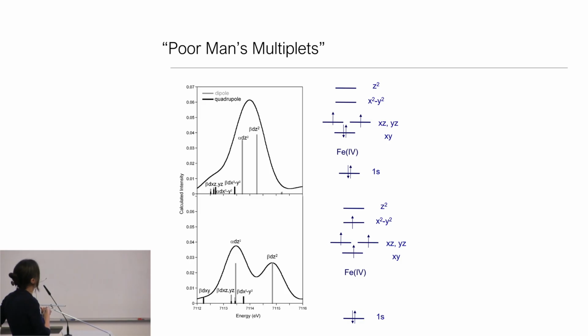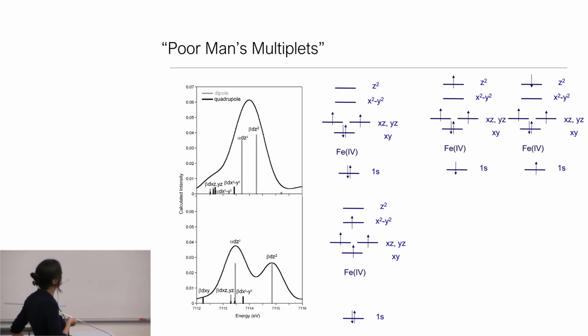If we look at iron 4 oxo, I'm showing here now just the 1s and the C4V splitting of the d orbitals with a ground state triplet versus a ground state quintet. And what you see in the triplet case is that if I think about this being dominated by the DZ squared, I could put either an alpha or a beta electron in the DZ squared. And so these transitions I calculate in TD-DFT, the alpha and beta DZ squared, these are locally quartet and doublet states that are actually just split in energy due to spin polarization.